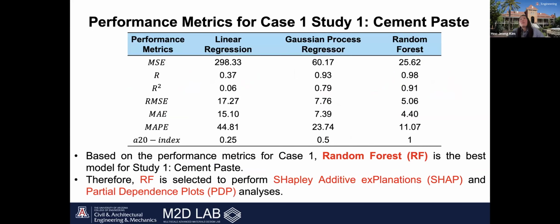And to validate the parity plots, we used several performance metrics to see which machine learning model performed best. And for these metrics, lower values are better for MSE, RMSE, MAE, and MAPE, while higher values are better for R and R square and the A20 index. And based on this result, the random forest model was confirmed as the best performing model, and we then used the random forest model for further analysis, including SHAP, Shapley additive explanations, and partial dependence plots, or PDP, to better understand how each variable affects the compressive strength.